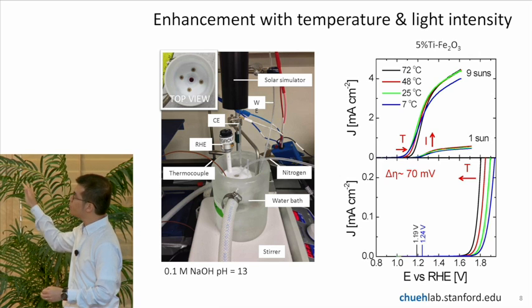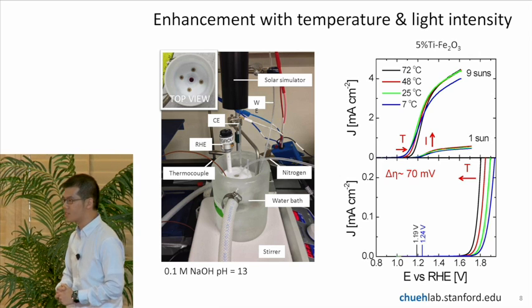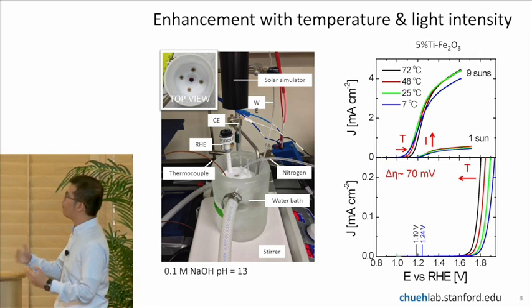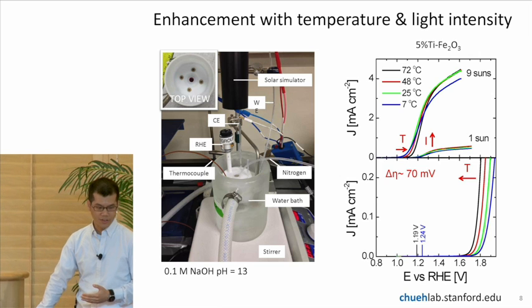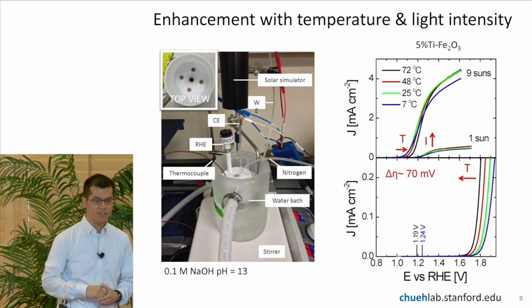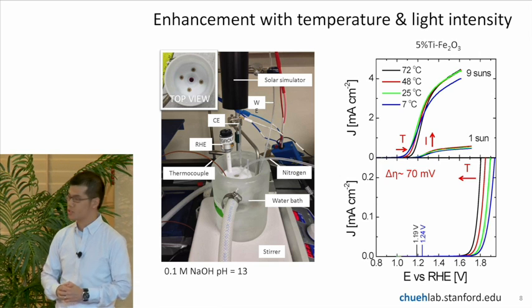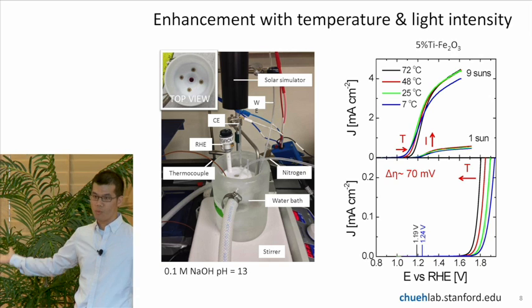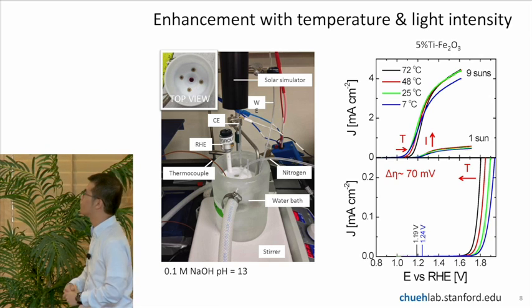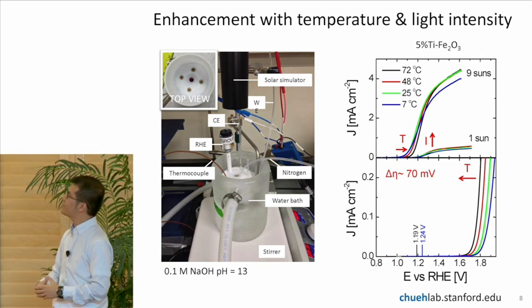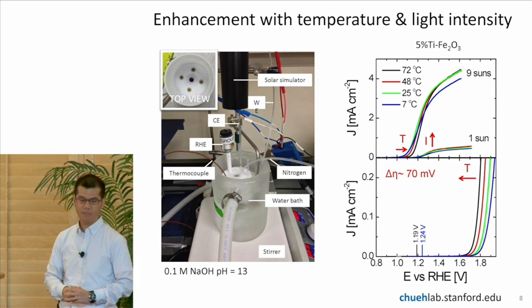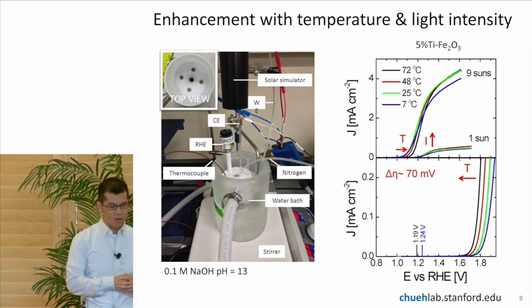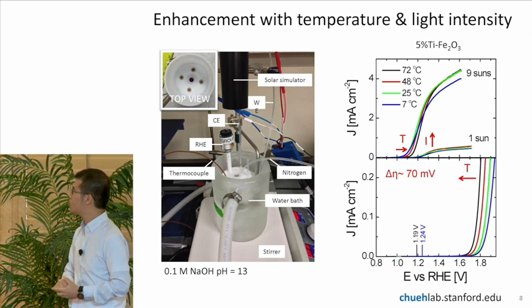So what I'm showing you is several curves of these iron oxide semiconductors at various temperatures, starting from 7 degrees Celsius to 72 degrees Celsius, at 2 different optical concentrations. So again, we have 1 sun, so that's what we have out there. Not today, but if the sun was out, it would be 1 sun. And then 9 times that, okay? So I want to point out several critical features of the plot.